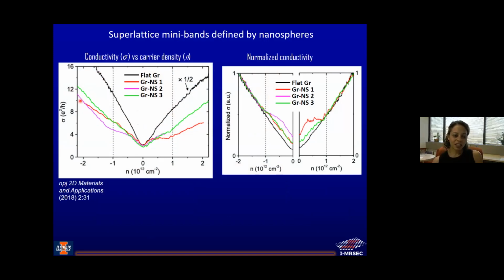And you can kind of see in the raw data, if you just look at the magenta one, it goes down, and then the slope changes, and same thing for the green and the red one, it goes down, and the slope changes. That's a little bit hard to see here, so what we ended up doing is just normalizing the high density regions to that of a flat graphene, like here, and then seeing how it varied around the low density regions.